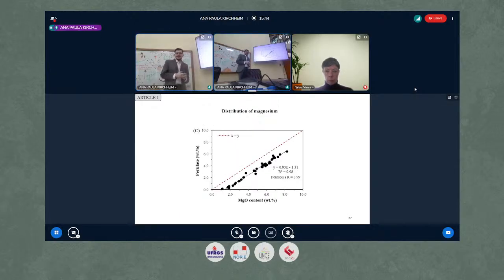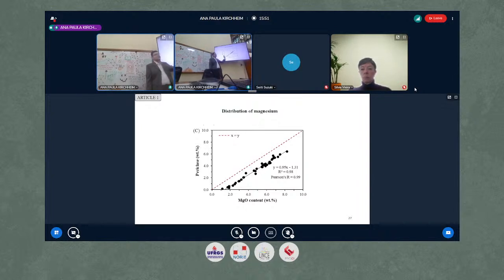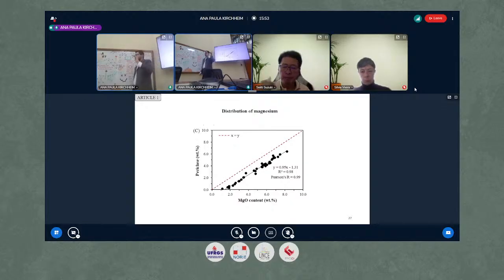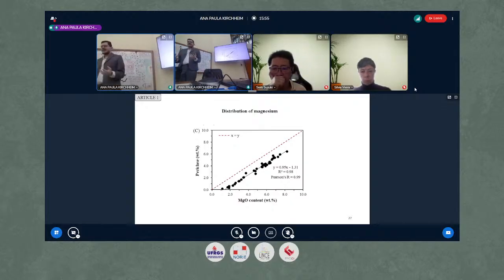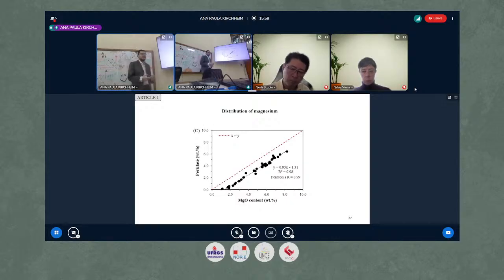And also we see something like this. We see that up to 1.7 to 2% of magnesium is incorporated in the main cement phases, while the excess will form periclase, with a very strong linear correlation.